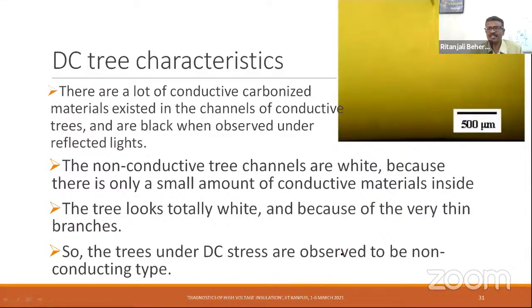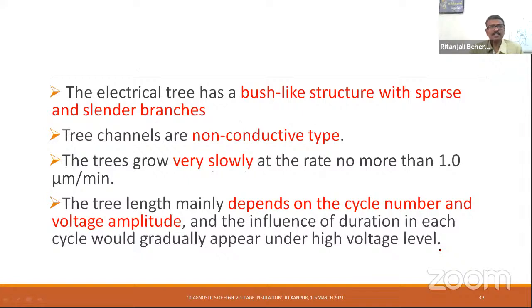So the trees under DC stress are observed to be non-conducting type. That is another observation in the DC. As far as the DC is concerned, the tree is like a bush-like structure, or we can call it more of a branch kind of structure with slender branches, and they are non-conductive because they are very, very white in color. The trees grow very slowly at the rate of 1 micrometer per minute. This is because of the higher applied voltage. And the tree length mainly depends on the cycle number and the voltage amplitude. So this is about the DC tree.